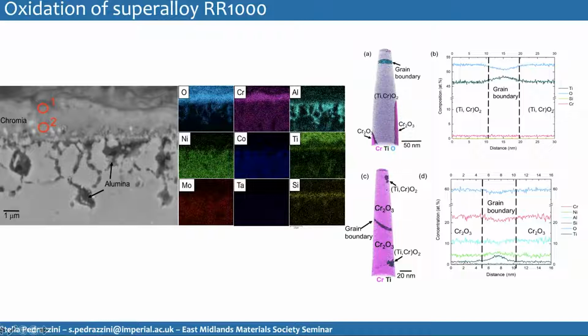And then in needle number 2, lower down into the oxide scale, this is chromia. So we got the composition of the chromia, and what is interesting is here, unlike the rutile, we have the oxygen, we have chromium as expected, but we also have some aluminium in solid solution and some nickel and some titanium as well. So it's quite interesting to get an idea of the exact chemical composition of the sample, because chromia is not really stoichiometric chromia in this case. And at the grain boundary, a concentration profile going across this grain boundary will tell us that there is a depletion in oxygen, and there's an increase in titanium there as well.